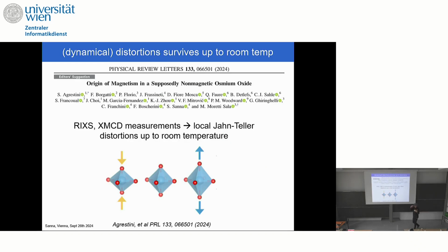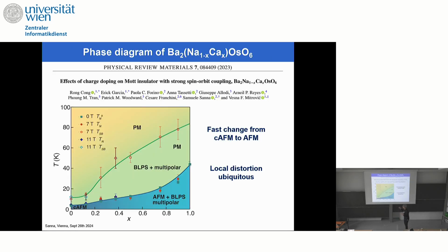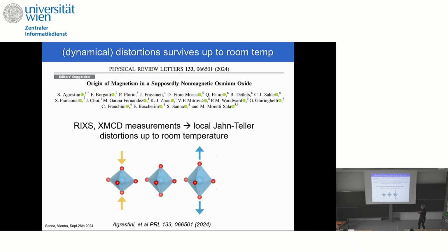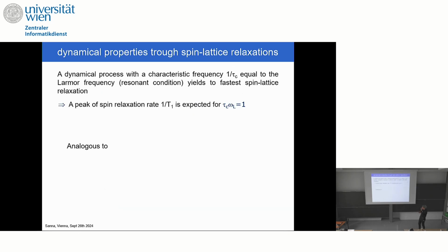So anyway, just to remind what Marco was saying this morning, even at high temperature, at room temperature, a very fast probe can detect that there are dynamical Jahn-Teller distortions. So probably what we are looking at here is that they are frozen in the scale of the NMR, which is typically a very slow scale, okay, so quasi-static limit. And now, what about the dynamics?